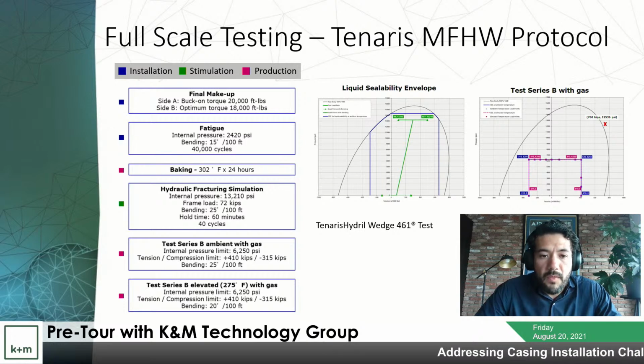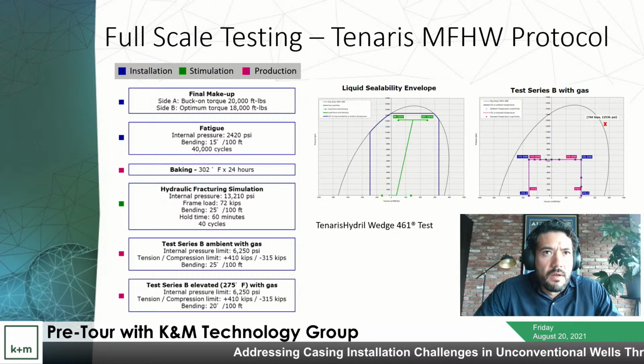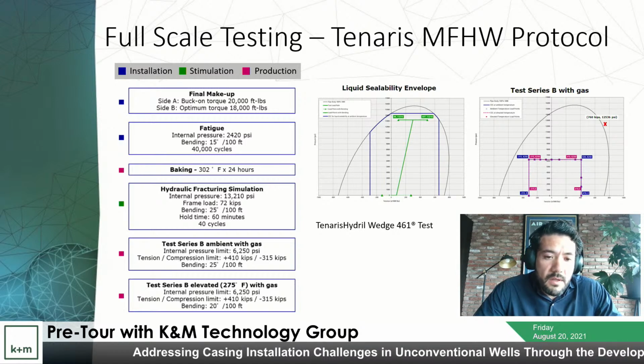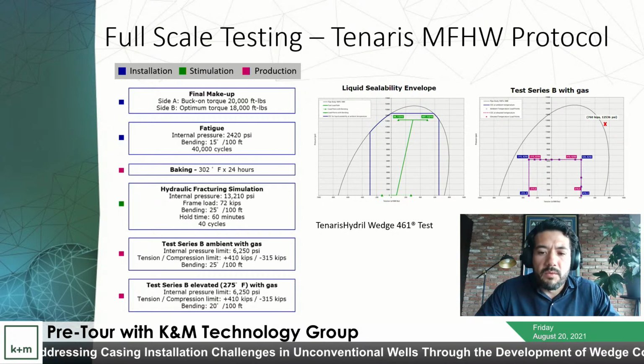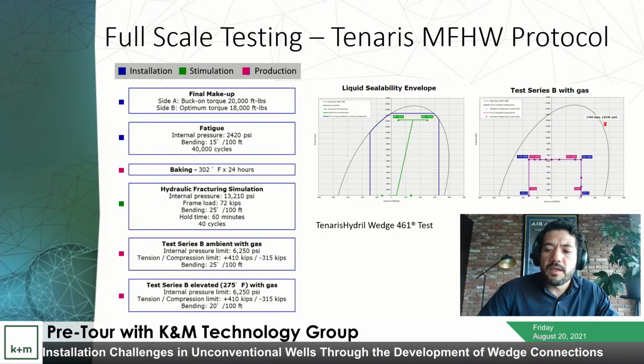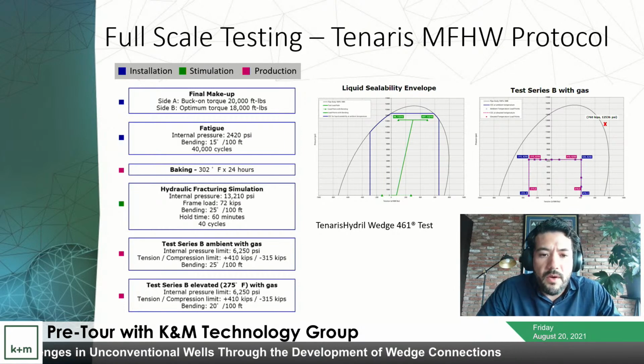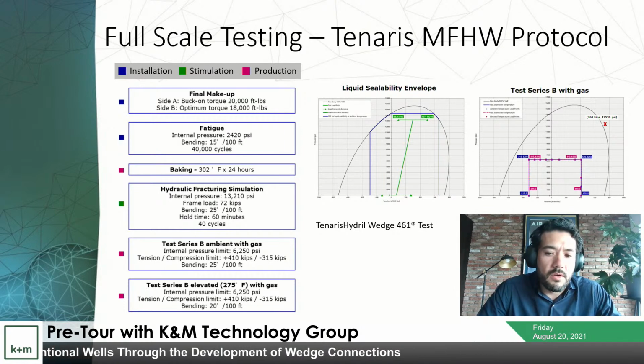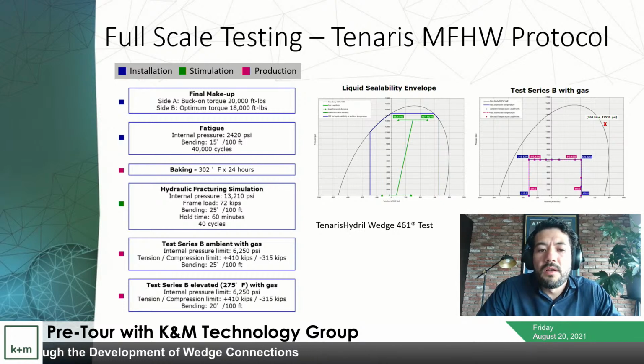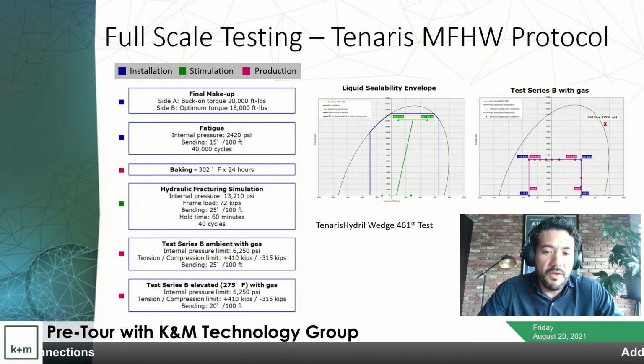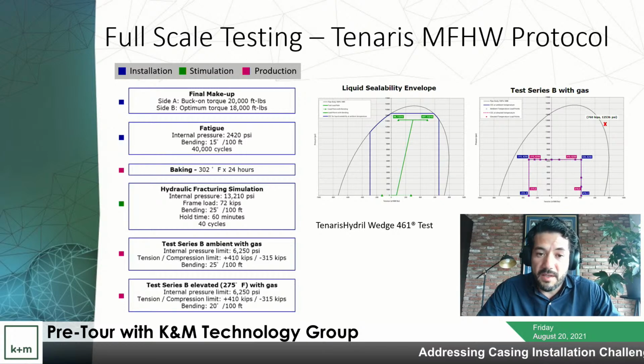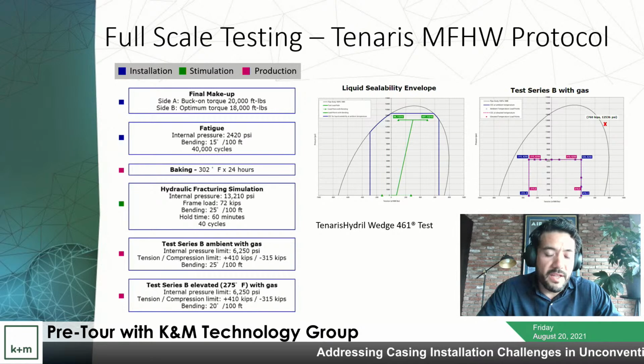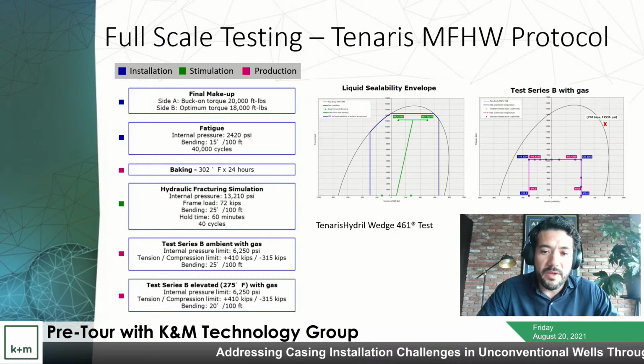So really, that aging of the thread compound, we've seen that sometimes it does play a role. For this part of the test, we did it at 302 Fahrenheit for about 24 hours, and that's good enough time to impoverish the conditions of the dope. When you see a thread after being through this and without, it's really like powder. It's really bad.